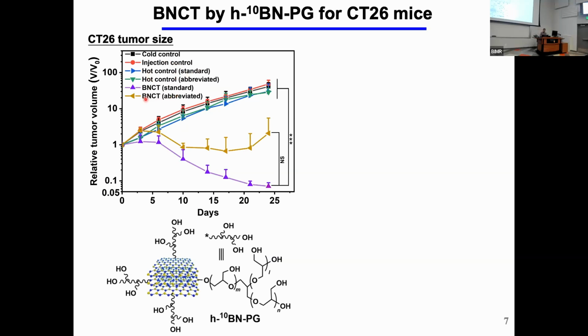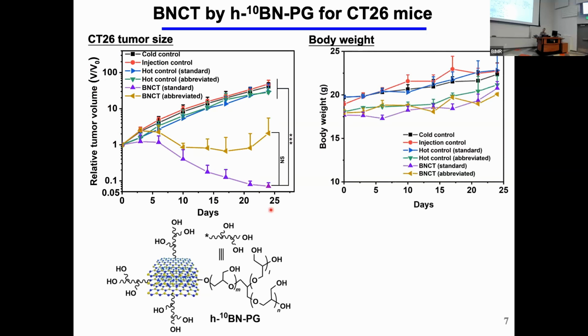So you can see that under these standard conditions, we start the relative tumor volume from 1. The control gets larger and larger, on a logarithmic scale. But only with BNCT does the tumor volume decrease from 1 to almost 0. That means almost all the mice were fully treated and cured, and the efficacy is very good. And of course, no acute toxicity has been observed.